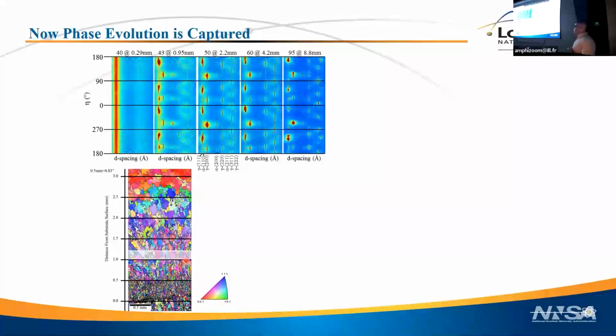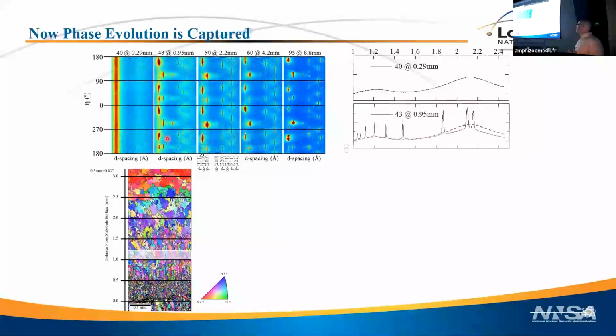This is what a series of diffraction patterns looks like if you unroll them. So here's liquid material, and this is right after it solidifies, less than a millimeter away from the melt pool. And you can see the texture already in there. Here's that fourfold symmetry that I told you about earlier in the austenitic 200 peak. And it's hard to tell here, but that develops a little bit with time. But one of the first things you catch is that the texture really happens right away. It's formed right away in the process when it solidifies.